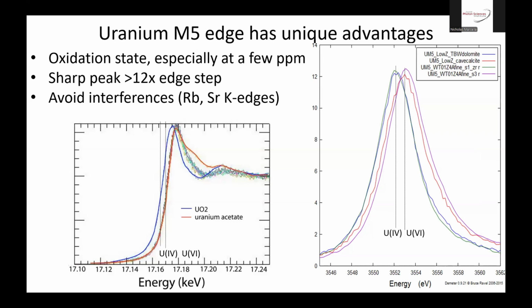But the M edge is much lower energy, only 3.5 keV instead of 17. And it shows a very sharply defined peak that's also distinguishing between the two oxidation states. The interesting thing about this is in this plot, you can't even see the edge step, but it's really small. The peak height is about 12 to 15 times the edge step height. So it's a very much amplified peak.